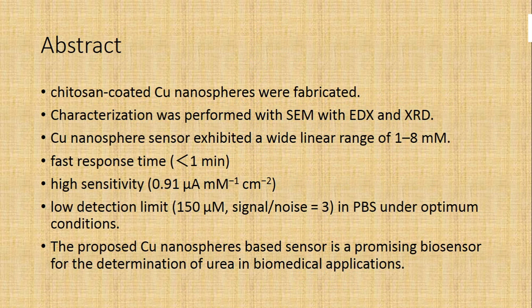Briefly, we accomplished the following. Chitosan-coated copper nanospheres were fabricated. SEM plus EDX and XRD were used for characterization. The copper sensor had a linear range of 1 to 8 millimolar. Response time was fast, less than a minute. Sensitivity was high. Detection limit was low in PBS under optimum conditions. The proposed sensor shows promise for urea detection in biomedical applications.